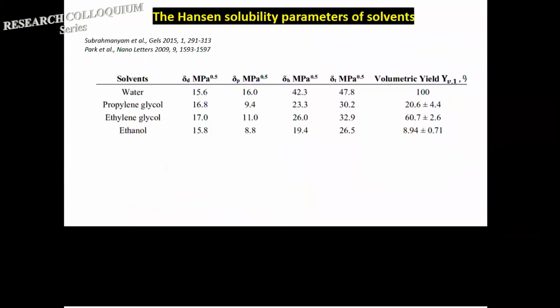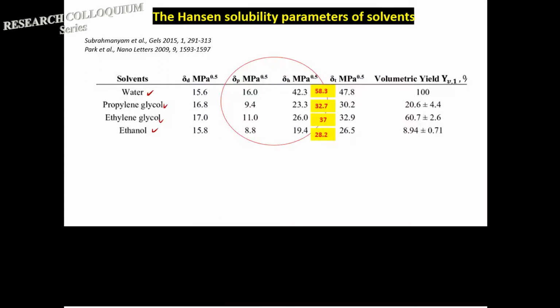In order to further understand the fundamentals behind the solubility of this graphene oxide in different solvents, we try to correlate it with the Hansen solubility parameter. Now, all the solvents that we are working on, except engine oil, okay, engine oil is not inside this category over here, have their own Hansen solubility parameter. Okay. Now, according to literature, by adding the parameter for the polar bond and the parameter for the hydrogen bond over here, you can know the solubility of your graphene oxide. By adding the delta P and the delta H over here, you can identify the ranking, how well your graphene oxide can dissolve in it. For example, this one is the highest one.